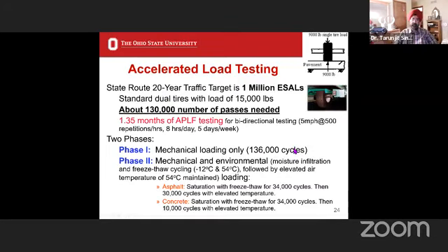What we were also interested after that is to see what about environmental effects. Most pavements fail because of moisture infiltration. And here in the US, because we have freeze-thaw cycling, we were also interested in freeze-thaw cycling. And so after doing phase one, in which we tested both the concrete and asphalt pavements with 20 years of highway traffic, we then exposed both of them to an additional 34,000 cycles, as you can see. And the asphalt one obviously was for freeze-thaw and elevated temperature, and the concrete one also. And in both the cases, we first saturated the pavement base to be able to test for the most intrusive or the worst loading condition.